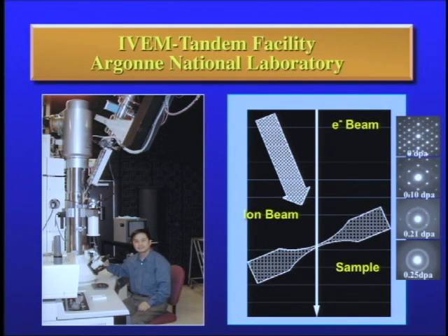Now, almost all of our experiments were done at Argonne. In a different building is your ion accelerator. Okay, these are not tabletop experiments. But all we want are the ions which come down this pathway and into an electron microscope. And so sitting at the microscope, you can start with the fully crystalline material and watch it become amorphous. You can put a heating stage around your sample or a cooling stage and do this as a function of temperature. And remember, the actinide or plutonium doping experiments took years, 4 or 5 years. The natural samples, 500 million years. This is a sequence in 15 to 30 minutes. Okay? Sometimes longer if you have to go to very, very high doses.